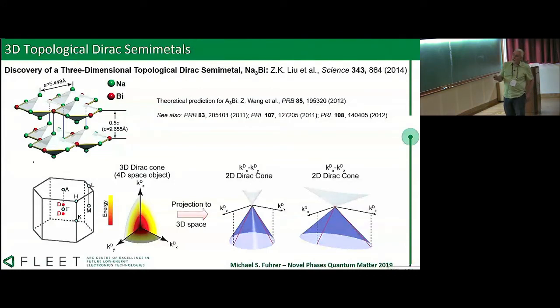The Dirac points in a 3D Dirac semimetal don't lie necessarily at high symmetry points. They lie, in this case, offset from the gamma point along the z-axis in the material. And there are just two Dirac points in this particular material. So you have, again, this linear energy momentum relationship. It's anisotropic, so the velocity is lower along the z-axis.